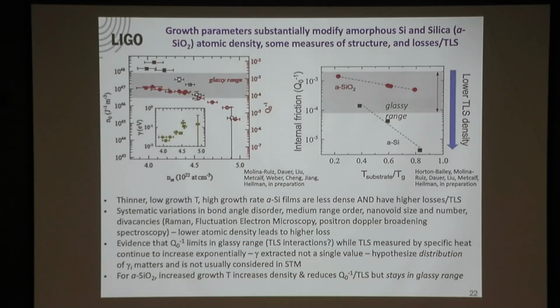We've already found that silica does not do this. So with silica, we can do the same thing. We can change the density. It's got a nice range of densities and a nice range of two-level states, but not those 3 orders of magnitude. All of our silica is still up in this universal range.